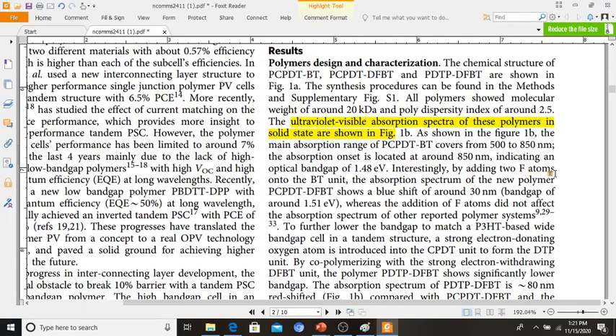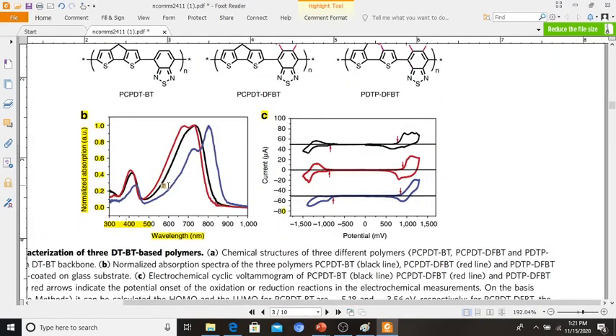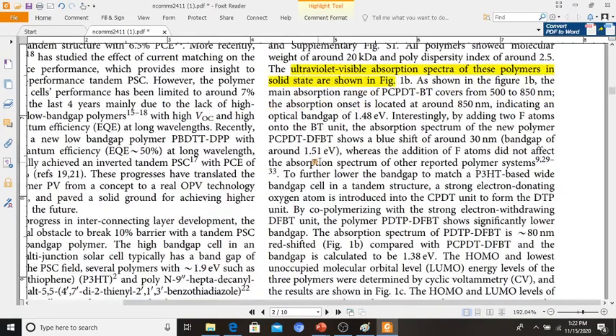Interestingly, by adding two F atoms into the BT unit, the absorption spectrum of the new polymer PCPDT-DFBT shows a blue shift of around 30 nanometers. You can see that it is shifted by 30 nanometers, so it is a blue shift. The band gap is raised to 1.5 electron volts, whereas the addition of fluorine atoms did not affect the absorption spectra of other reported polymer systems. This fluorine effect is not reported in other systems, but here it has an effect. The lower band gap matches P3HT, due to oxygen doping by the furan.